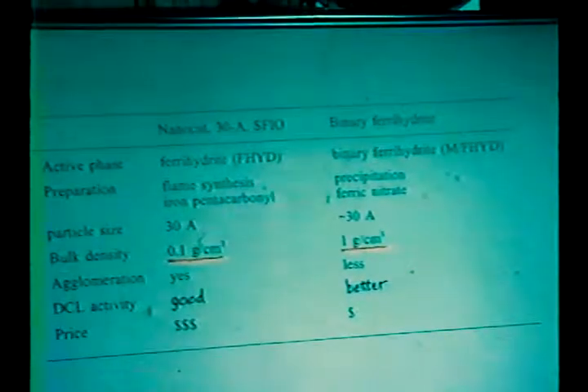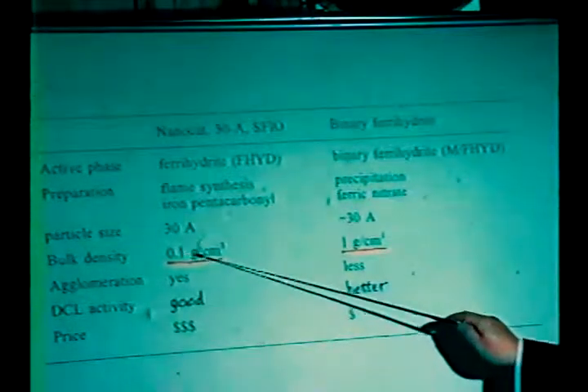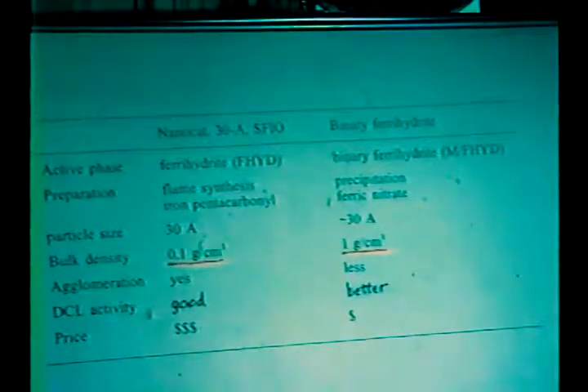The bulk density means if I just measure the density without pressing the powder. This is very light, 0.1 gram per cubic centimeter. Our sample is 10 times that. Why? If you look at the TEM picture, it's clear.